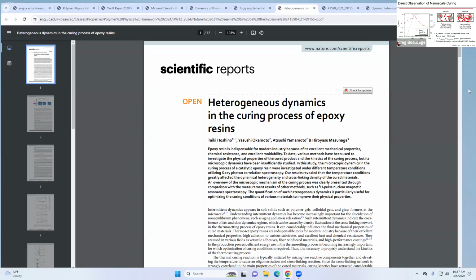Yeah, right here. So in blue, that's the temperature. During the temperature ramp, we saw an increase in the velocity, an increase in the dynamics. So things are moving around. We're heating that system up. And then literally as soon as we hit 120, that thing drops like crazy, over almost 2 orders of magnitude in the dynamics. All right. So the cross-linking reaction can be tracked in situ at the nanoscale using that process right there.